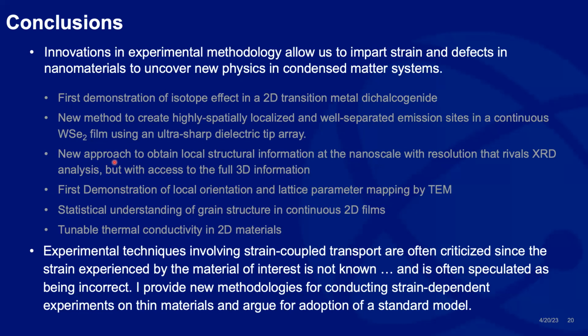With respect to electron microscopy, we can now get local structural information at the nanoscale with reciprocal space resolution, because we're accounting for instrument broadening and the instrument response function, that rivals XRD analysis. But it gives information about the whole three-dimensional nature of the crystal, because we can collect all the different HKLs, which give us out of plane information. We've done a demonstration of orientation and lattice parameter mapping.